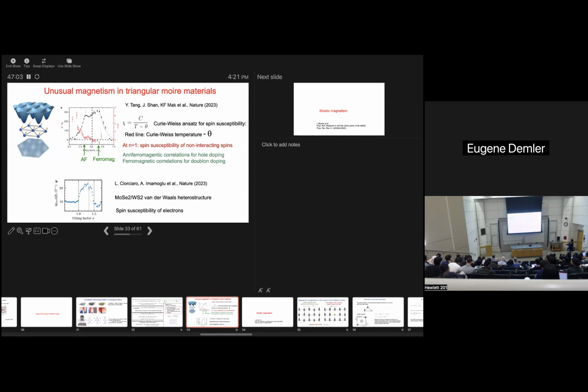So essentially, within the error bar, what is plotted, this red color, is minus theta, right? And what you can see is that exactly at 1 fermion per site, which corresponds to 0.5, within the experimental accuracy, spins behave as if they're non-interacting spins. That's very counterintuitive. Remember, in the case of square lattices, the strongest magnetism is exactly for 1 fermion per site. Here, it's as if there are no magnetic interactions. There is 1 fermion per site.